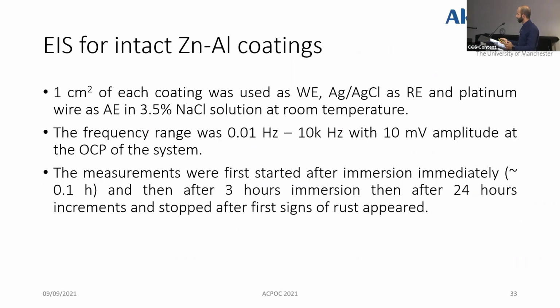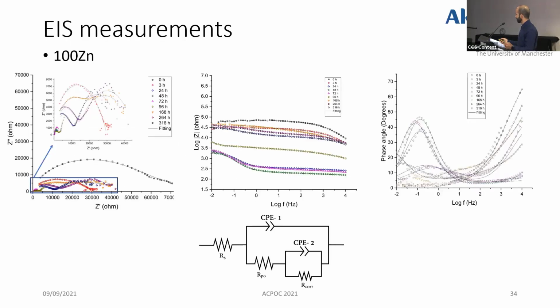For the EIS of intact zinc-rich zinc aluminum coatings, the same setup as the OCP experiment was used here, but the frequency range was 0.01 Hertz up to 10 kilohertz with 10 millivolt amplitude at the OCP of the system. So the measurement was started, the first one immediately after immersion, and then after 3 hours, then after 24 hour increments until the first sign of rust appeared, which is considered the moment of the coating failure.